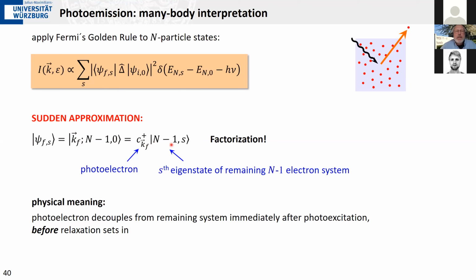The picture that I have is I take my photoelectron out immediately. The system has no time to relax. The entanglement has no way to do anything about this. I take out my electron immediately. So I have a creation operator where I put an electron into the state Kf, the final state Kf at my detector, and I have a remaining state of the n-1 system, which is the sth eigenstate of the remaining N-1 electron system. And I have to sum up over all such final states that can be reached by this process. There may not be a single one, there may be more than just one. But the picture again, sudden approximation means the photoelectron decouples from the remaining system immediately after the photoexcitation before any relaxation can set in.